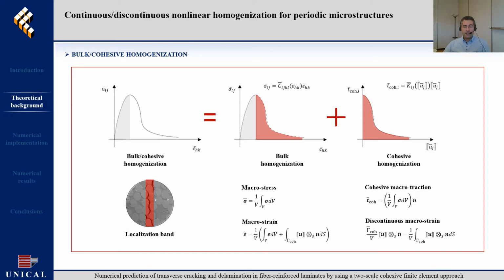In other words, the discontinuous part of the numerically derived overall constitutive response is obtained by extracting the portion of the loading curve after the appearance of a macroscopic localization band. Finally, a homogenized traction separation law is derived after suitably defining the microscopic cohesive traction vector and the macroscopic displacement jump. The main advantage of this approach is that a global traction separation law is derived through offline computations in a very efficient manner.